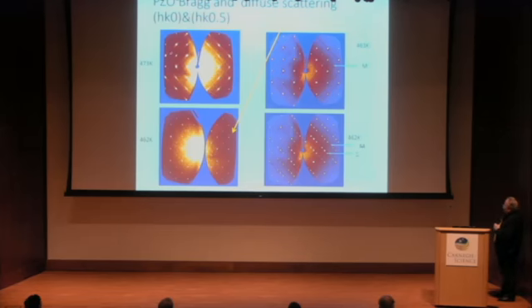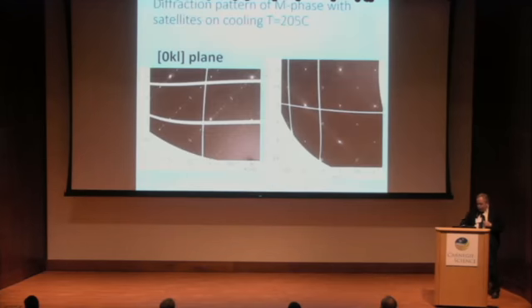So you see, this is high temperature, 473 K. In a very narrow region, we do see the M superstructure peak, 1/2. And if we go below, we do have, again, the M superstructure and the sigma superstructure. If you now look at slightly doped lead zirconate titanate, so let's have a look. So 0KL plane. In two different planes, we have a slightly different picture, HK0 and 0KL.